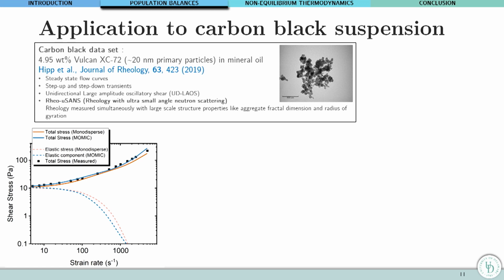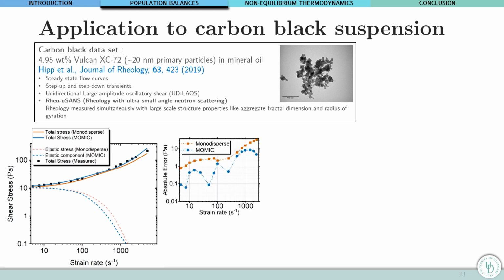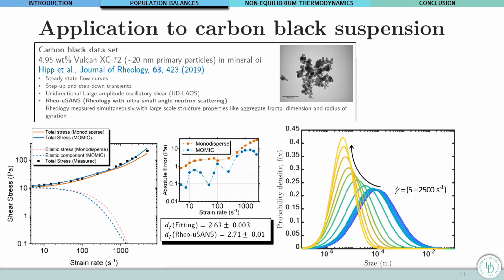The next evolution was to use this MOMIC approximation, which stands for moment interpolative closure, where we assume a certain distribution of the sizes, in this case a log normal distribution, and we were able to accommodate more faithfully the change in size. We did that approximation for a better behaved system which didn't have all the complexity of human blood, that is, a carbon black suspension. And what we were able to show, as you can see now, is that for steady-state data we are now able to achieve a quantitative fit. And also, what is of importance, of course, the errors are uniformly much lower than the monodispersed previous approximation. And even more importantly, we did generate some data.